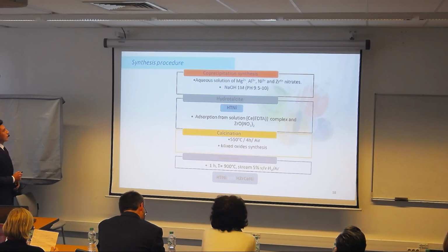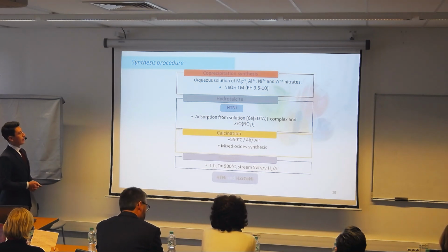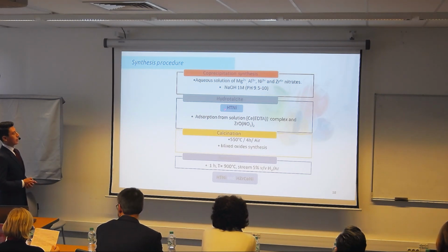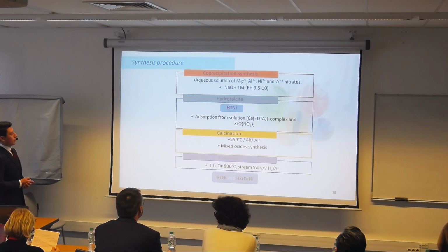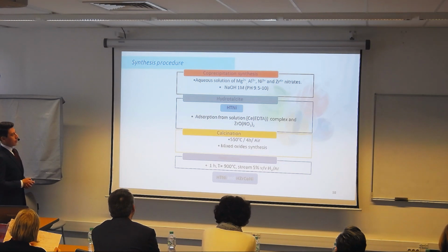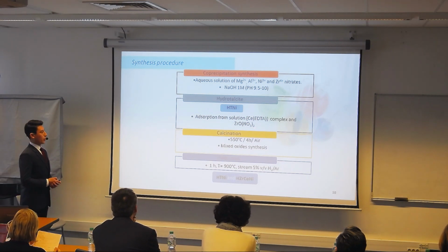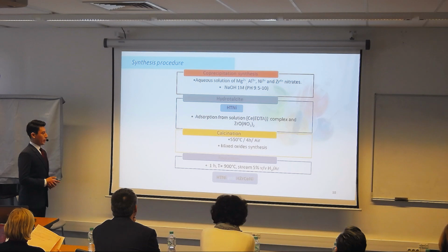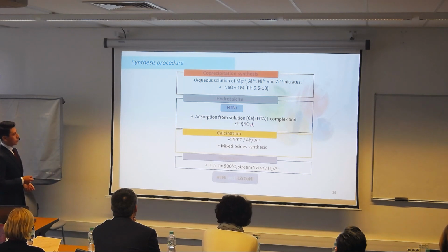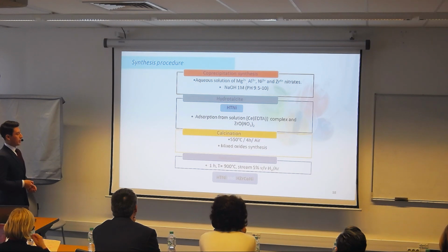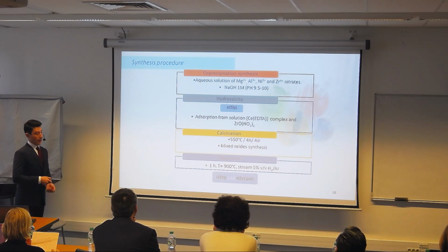These catalysts were prepared by the co-precipitation method, and so we deposit the nickel by this method. We have in the end this catalyst. For the promoted one, we introduce the zirconia and ceria by the adsorption method. So in the end, we have these two catalysts, the one with just the nickel and the hydrotalcite-derived one, and the promoted one.